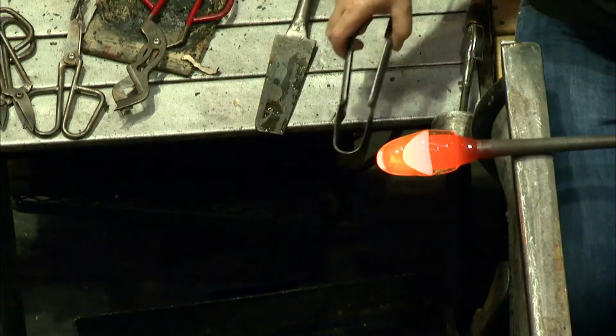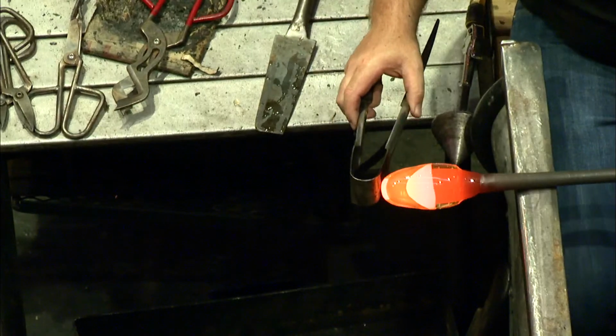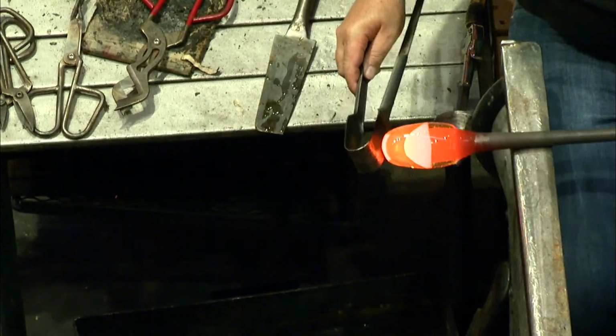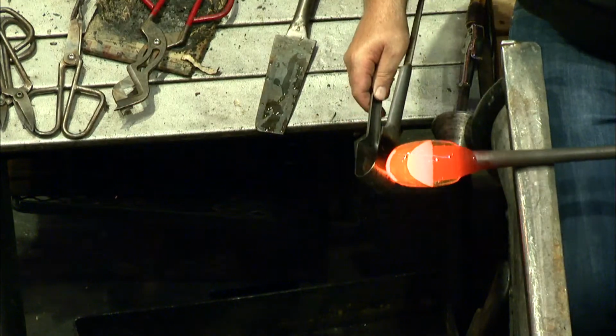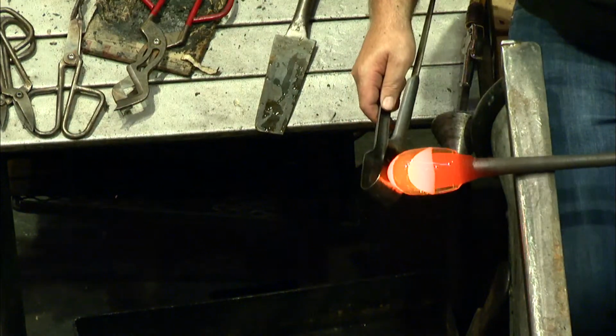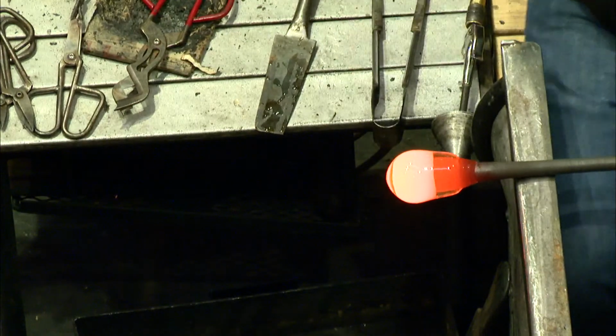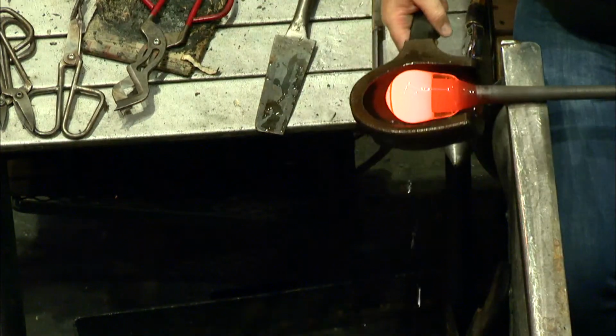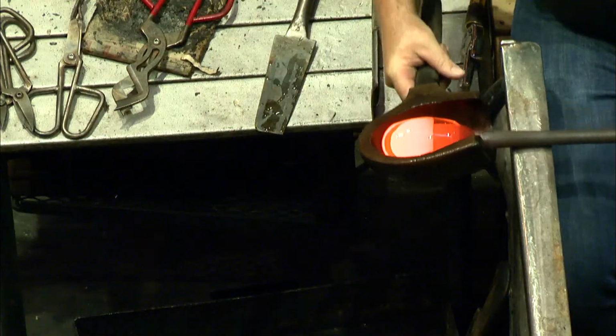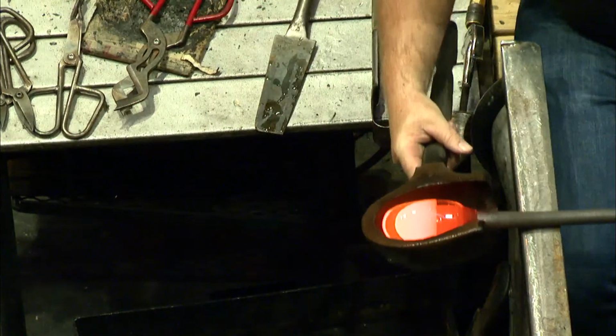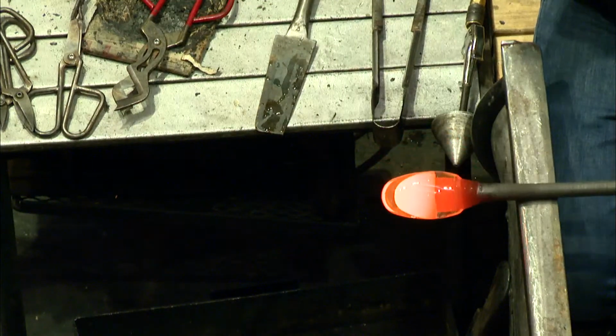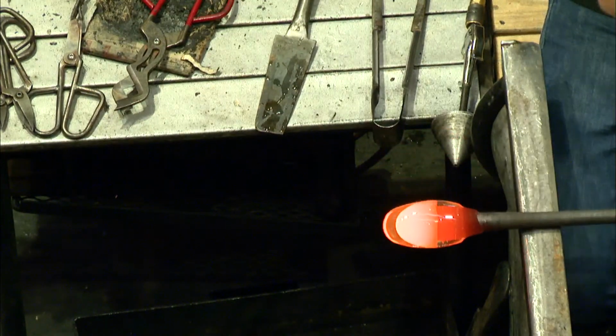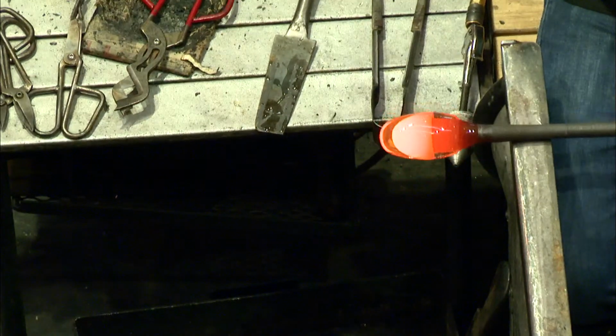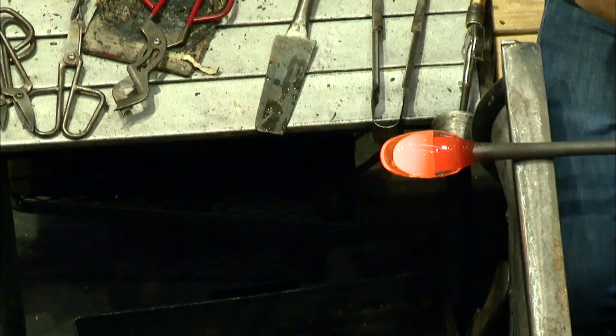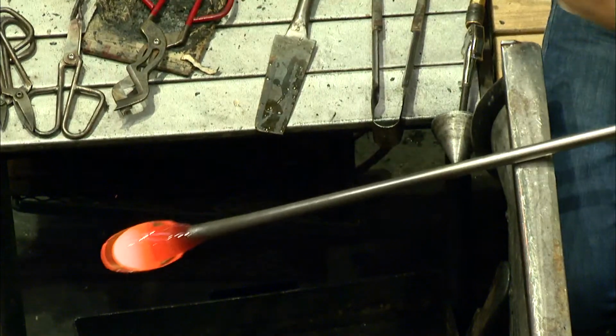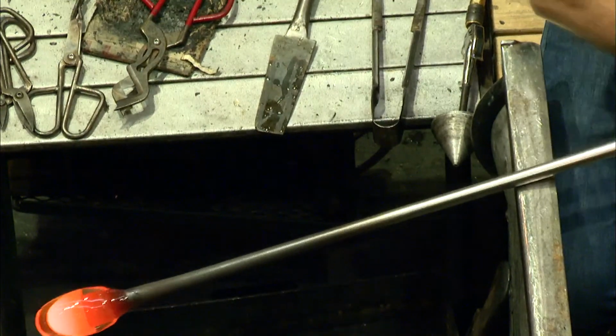Now, what prevents it from turning into a puddle in the annealer is kind of two things. One, it's the control on the annealer, keeping it at just the right temperature so the glass isn't moving and flowing, but it's also still warm enough that it's not cracking and breaking. But also the length of time that you keep it in that annealer. If you kept it in the annealer at 900 degrees for several days, that glass would begin to warp and change a little bit over time. But they only stay in the oven at that temperature for a few hours, typically throughout our workday, and then it'll very slowly come down to room temperature overnight.